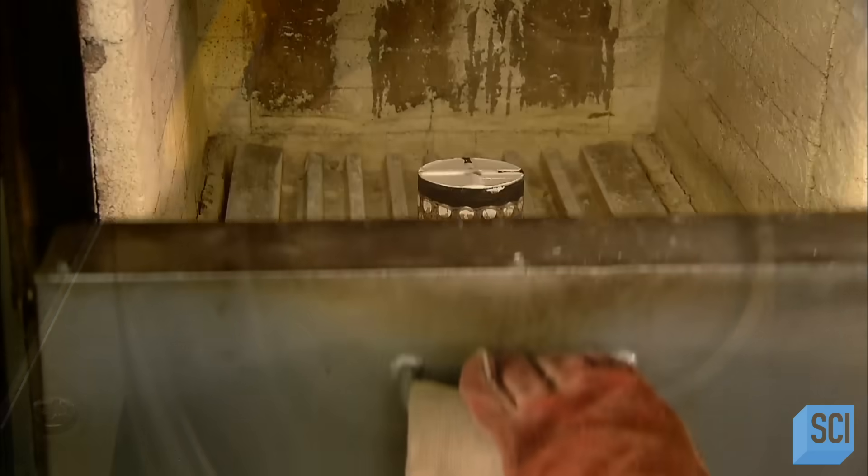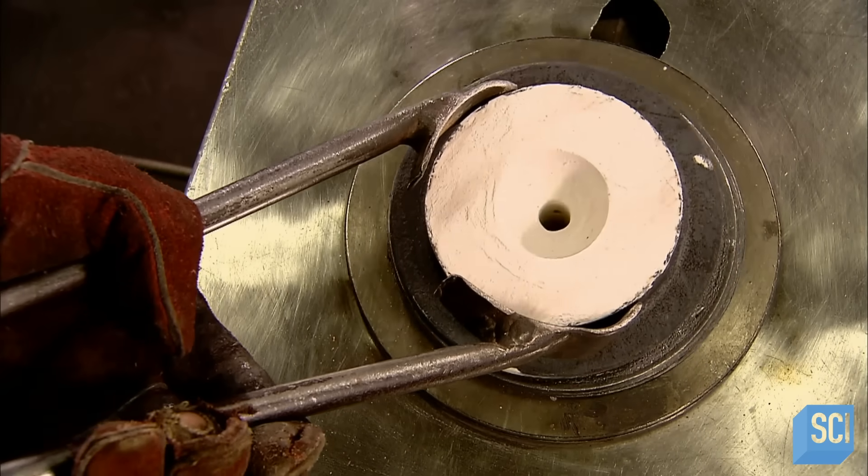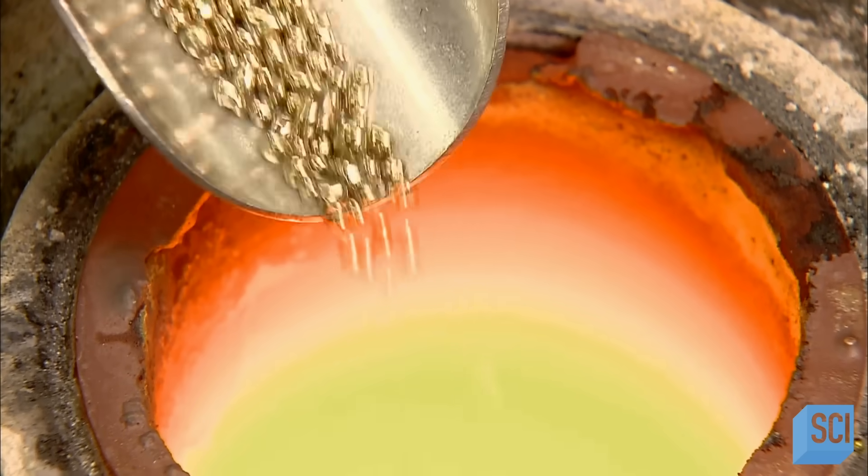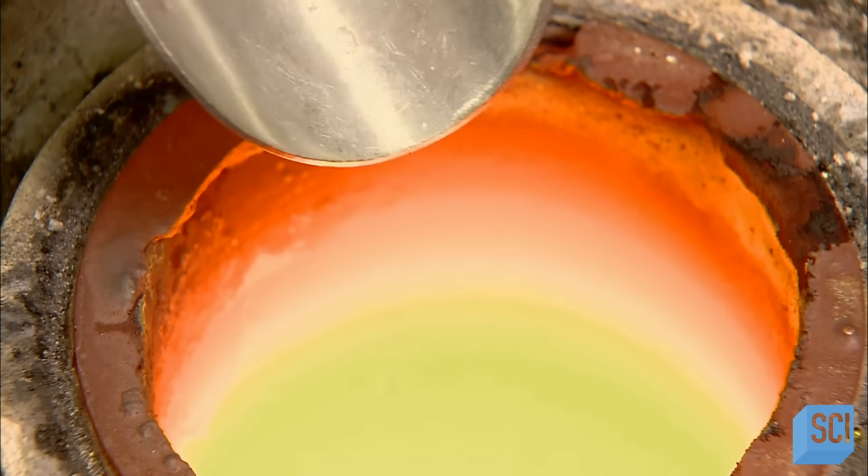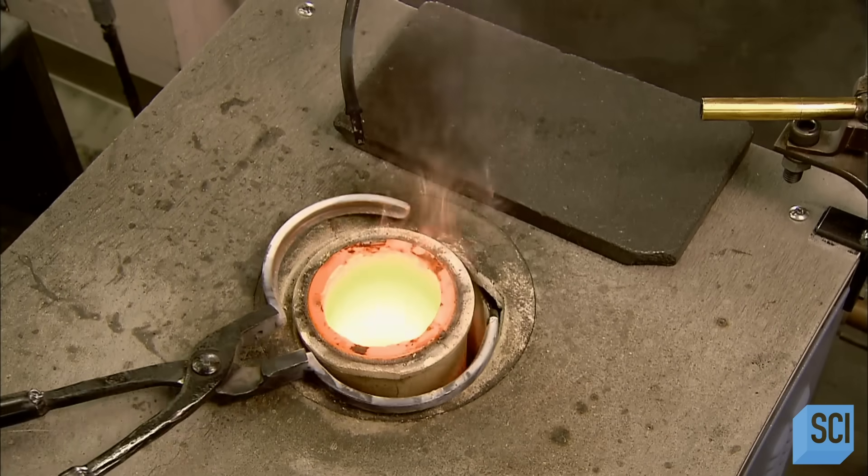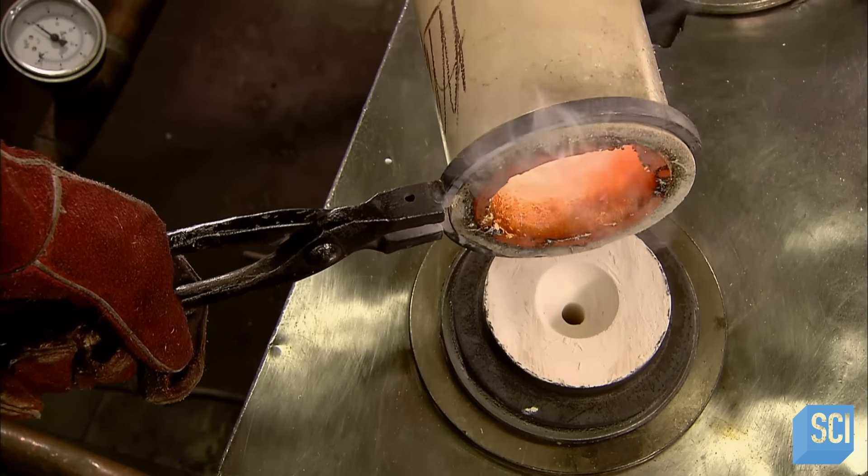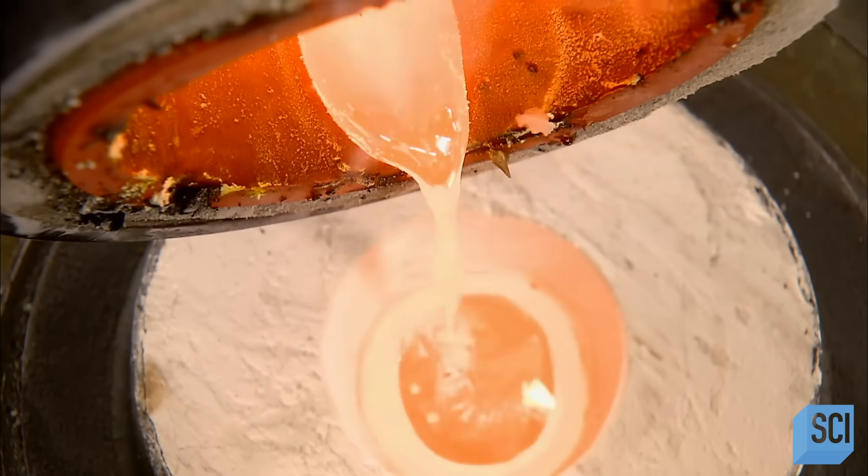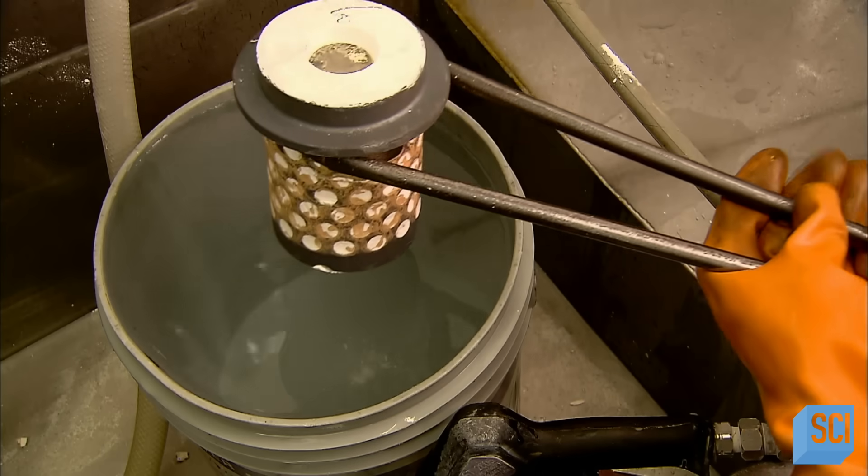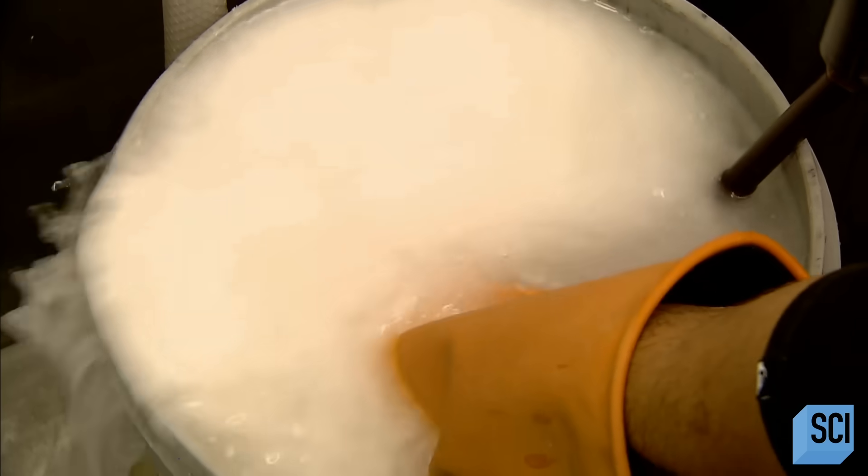They place the cylinder in a hot oven. This burns out the wax components, leaving behind a cavity in the shell shaped precisely like them. Now it's just a matter of melting down the metal for the final casting. In just minutes, the induction furnace has heated the metal, in this case gold, to the required molten state. They carefully pour it into the plaster shell. Gold flows down channels and into cavities left when the wax burnt out. Once the gold cools and solidifies, they submerge the shell in cool water. This instantly dissolves the hot plaster, releasing the cast piece.